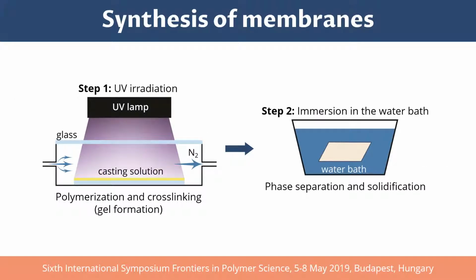As we can see for membranes, the first step is UV irradiation of the solution cast on the glass plate, which leads to the formation of the gel. The irradiation was carried out under nitrogen purging. The formed gel was then quickly immersed in the water bath to finalize phase separation and solidification of the membrane.